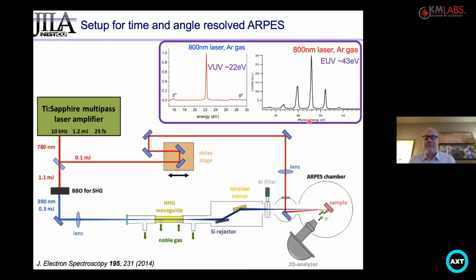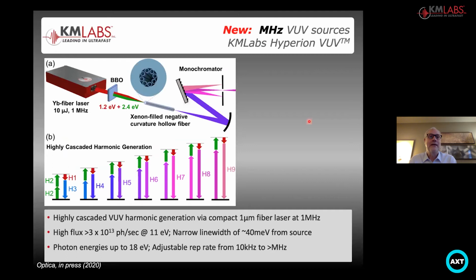Then you would have the pump and the probe hitting a target, generating photoemission that is then picked up by an analyzer. And work to date has generally used 2D spherical angle resolved photoemission systems. And there are very many of these around worldwide, and they're all amenable to use with high harmonic generation sources.